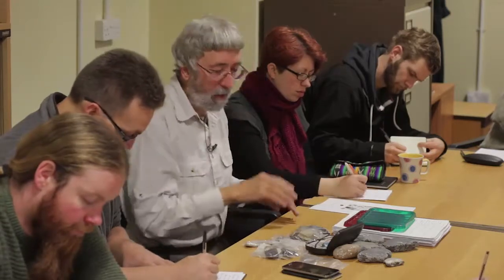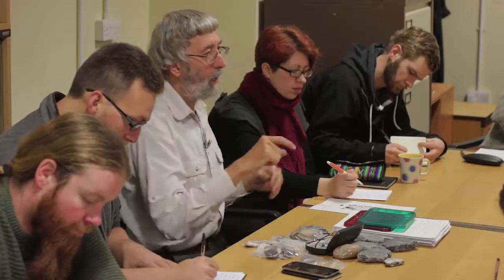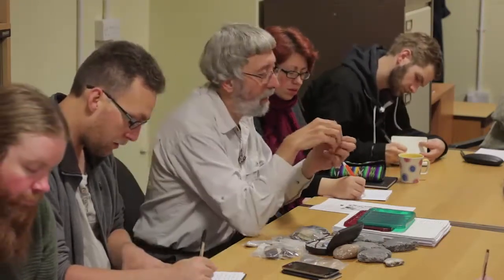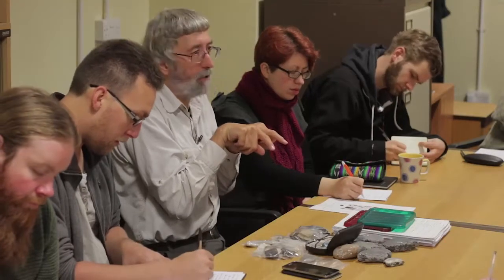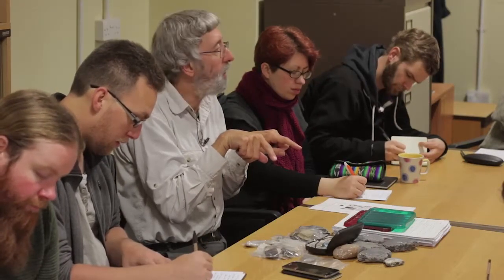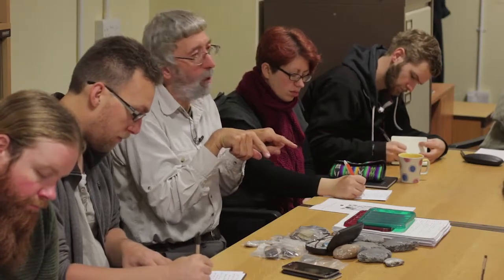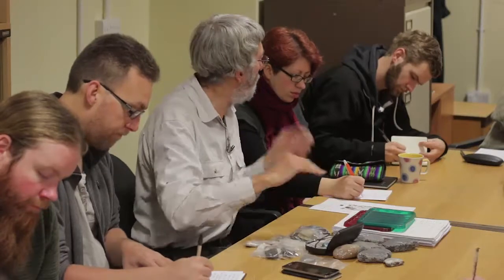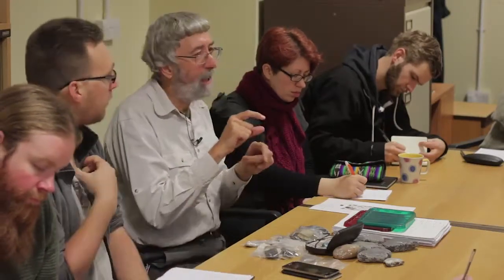But also, because of the nature of quartz as a mineral, the way the quartz is structured is that it is not equal in all directions. It has a preferred symmetry, and it will expand as it's heated in one direction rather more than in the other direction. So it sets up stresses internally, and those stresses can lead to microfractures at a very, very microscopic scale, which means that it actually becomes easier to flake. So you're making a more homogeneous material that's easier to flake. And if you want to make nice, lovely arrowheads, heat treating the flint is one way of making it much, much easier to make.